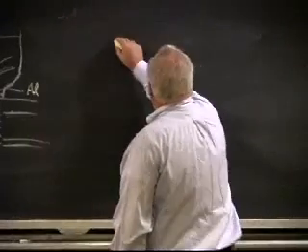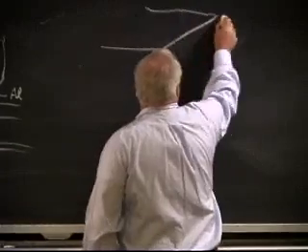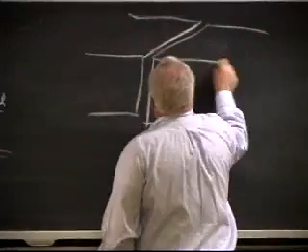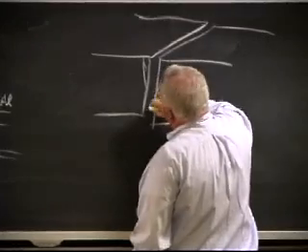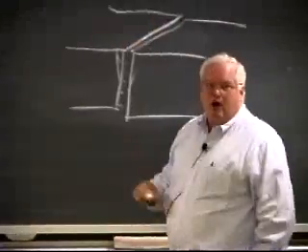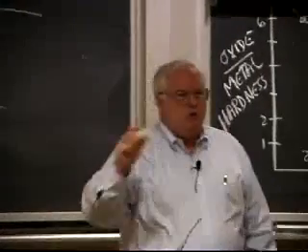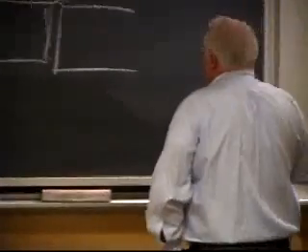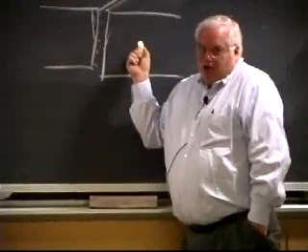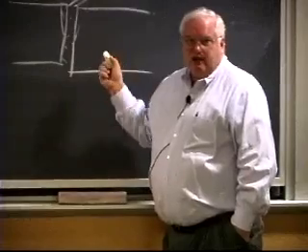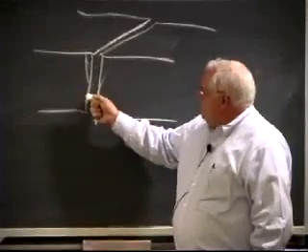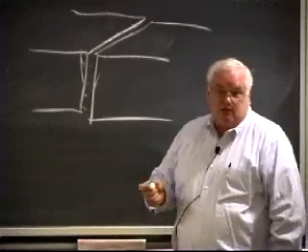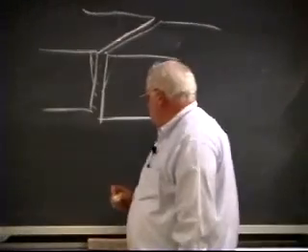And that was because they took this whole huge forging, and they basically beveled the edge, and they just put thousands of weld passes in here. And it had to be preheated to like 300 degrees Fahrenheit. So the guy's sitting next to an oven, and this is not a small oven. I mean, this weighs tons, right? So it's radiating back at him, and he's putting in thousands of weld passes. That's why it took a week. It took several guys a week to just put the weld metal in.